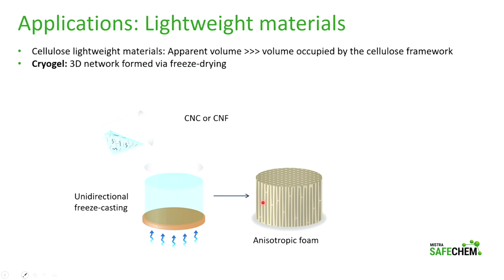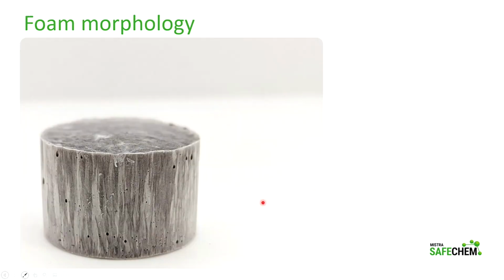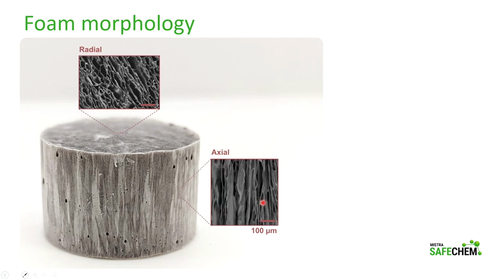And the reason that we want anisotropy is pretty much because we can tailor the properties of those materials. So we took the nanoparticles that I showed you before, and then we end up with this foam, whose porosity we characterize. If we look more into detail into this morphology, we can actually see that in the axial direction, you have these columns which are given by the template of the ice, and on top we can see a cross section where we can see elongated pores, which is also due to this templating technique.